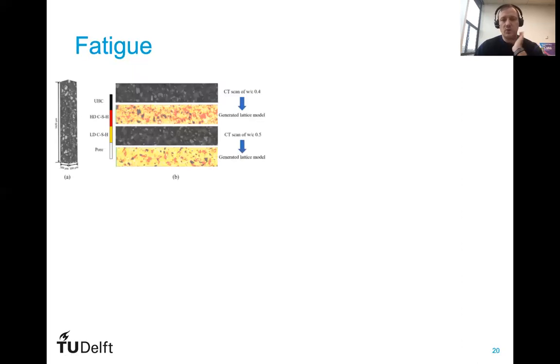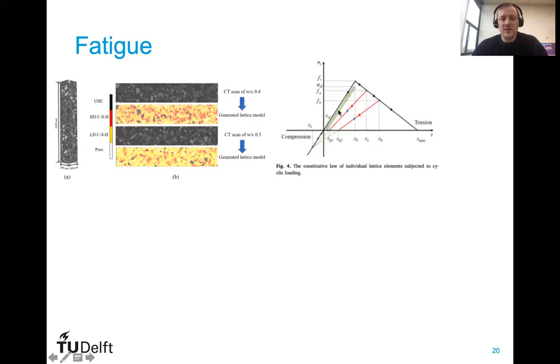Another phenomenon that we looked at is fatigue, the phenomenon of increasing damage with repeating loading in the cementitious matrix. So we repeated the same procedure where we have scanned micro cantilever beams. We also tested them using the same approach as shown before. And for different water cement ratios, we generated different microstructures for the model. In this case, we needed to have a bit more complex constitutive law where we needed to include also increasing damage in the matrix with load repetition and also unloading damages.